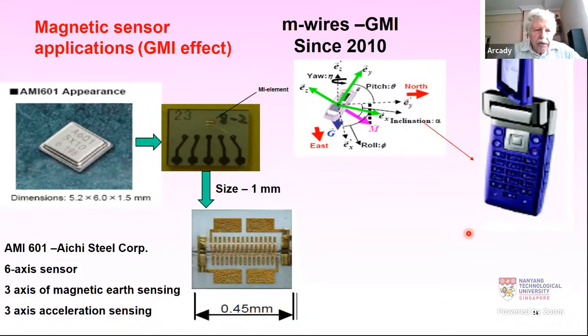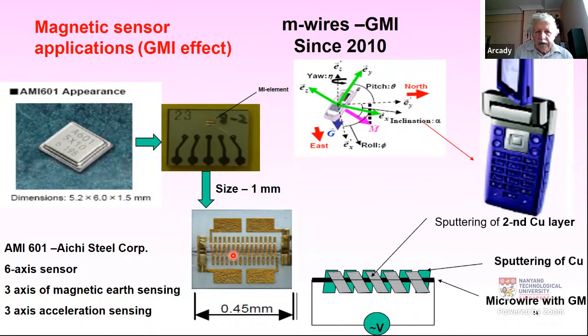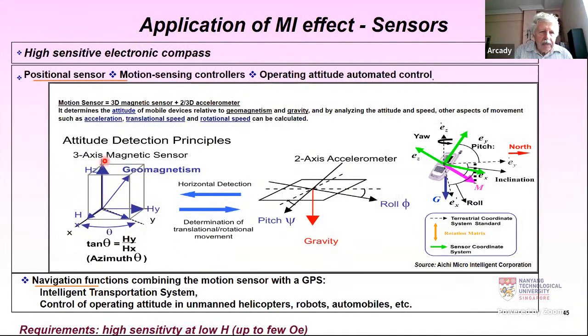Other applications are related, of course, with magnetic impedance chips, and in fact, Aichi Steel was involved in the preparation of MI chips. In this case, the size was about 0.5 millimeter, and the heart of this chip is the magnetic microwires placed here, and so it was proposed for use in quite sensitive MI elements for cell phones. And the principle is that you have 3 pieces of microwires placed orthogonally, and then we can measure the magnetic impedance in 3 dimensions. You can get the vector of magnetization in your MI chip.